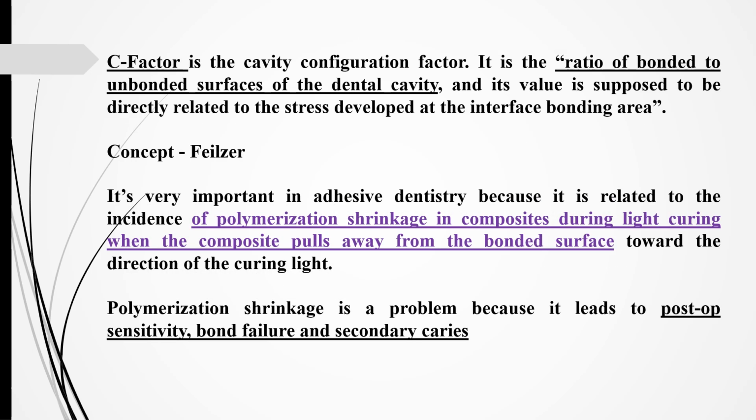So coming on to C factor, it is a cavity configuration factor. It is the ratio of bonded to unbonded surfaces of the dental cavity, and its value is supposed to be directly related to the stress developed at the interface bonding area. This concept was given by Feilzer.